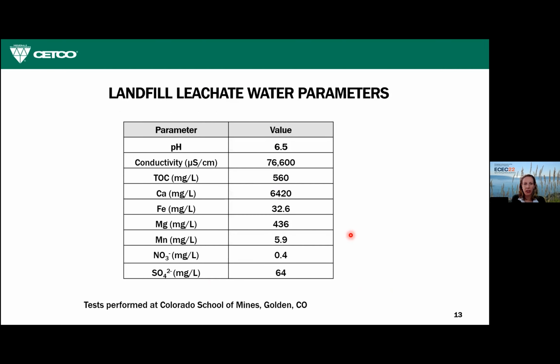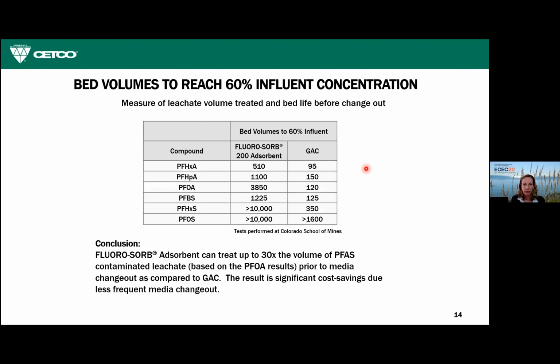This landfill leachate had a TOC of 560 milligrams per liter, so it's significantly higher concentration than most groundwaters. It's a high strength leachate. The conductivity shown here is really high. There's a lot of anions and cations.